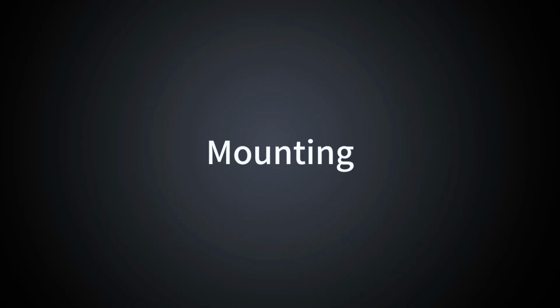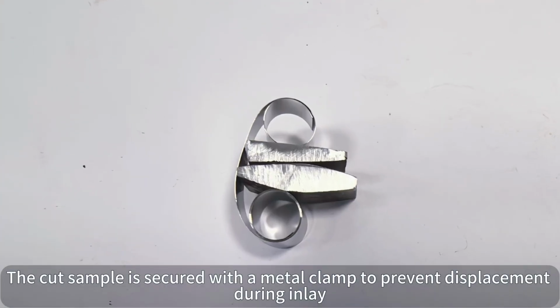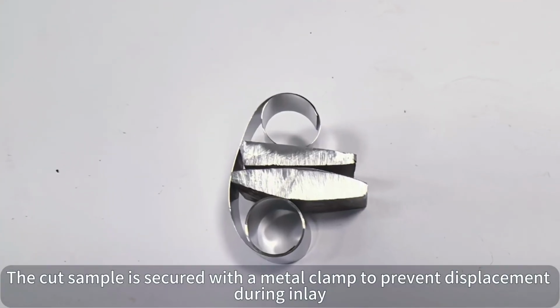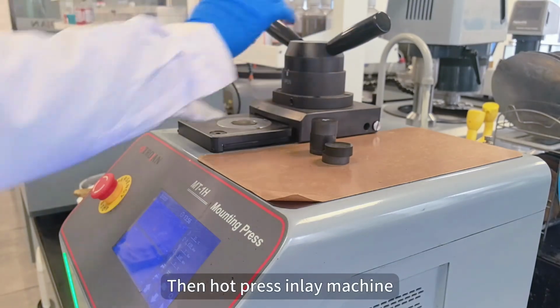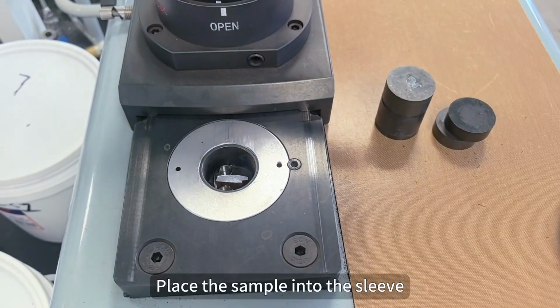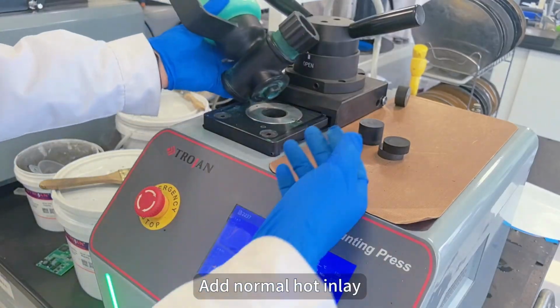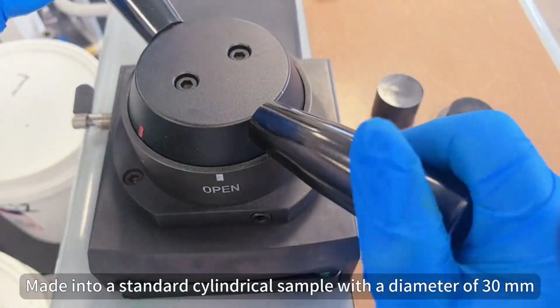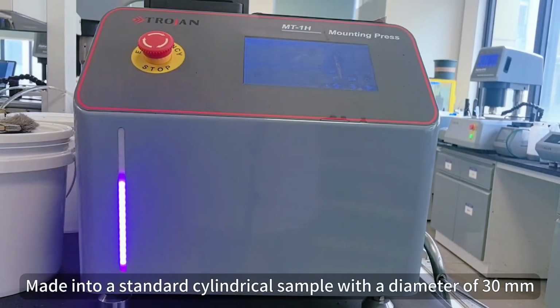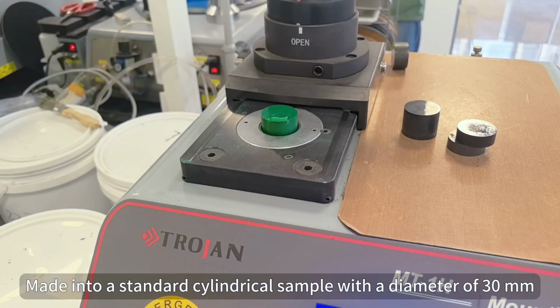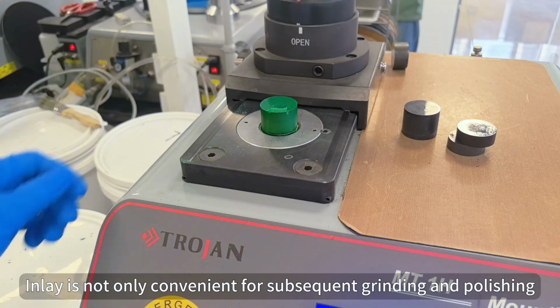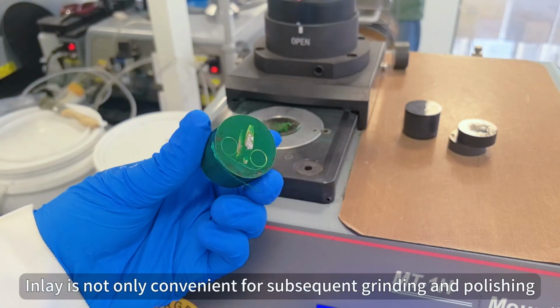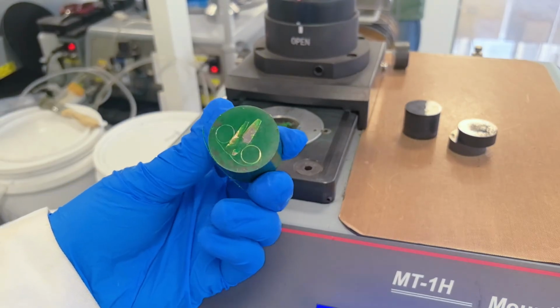Mounting. The cut sample is secured with a metal clamp to prevent displacement during inlay. Then, in the hot press inlay machine, place the sample into the sleeve and add normal hot inlay material under high temperature and pressure. It is made into a standard cylindrical sample with a diameter of 30 mm. Inlay is not only convenient for subsequent grinding and polishing, it also protects the edge.